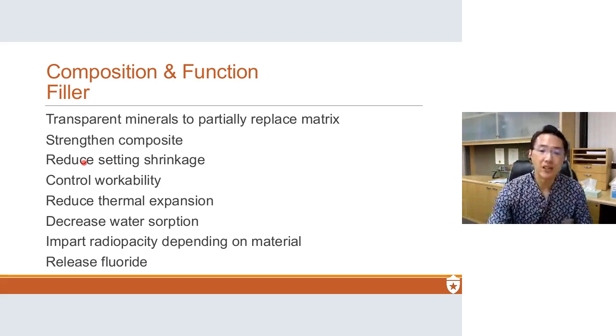So it controls workability. It reduces thermal expansion and contraction because it has a much lower coefficient of thermal expansion compared to polymers. Some actually are zero, close to zero. And they also decrease water absorption because they can't expand. And some of them, depending on if you use heavy metal particle fillers, which are usually used in small quantities, they impart radiopacity, and some can even release fluoride, depending on the material. Okay? Question here, does the presence of double bonds on both ends of TEGDMA make it more desirable as a monomer? Yes, because you actually end up getting a more cross-linked situation. Okay, and we will talk more about that, so good question.